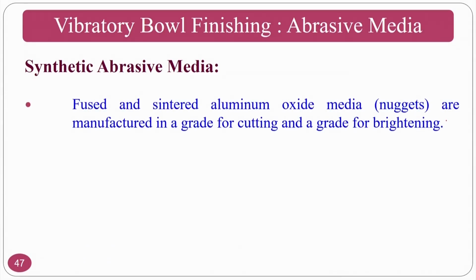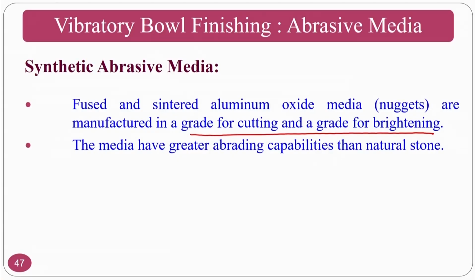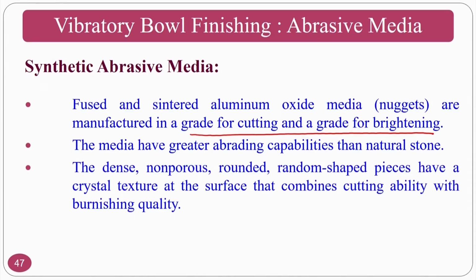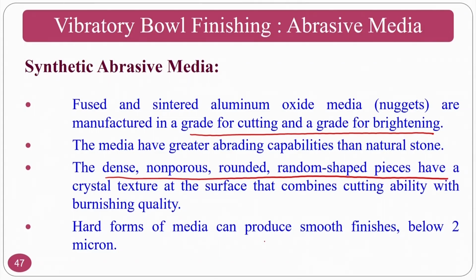In synthetic abrasive media, what we have to see is fused and sintered aluminum oxide medium. These nuggets are manufactured at the grade for cutting and the grade for brightening applications. If people want to get surface finish and good appearance also, for that purpose you can go for sintered alumina and other abrasive particles. The media have greater abrading capability than natural stone. That means silica and granite, whatever the particles are, their hardness is very low compared to aluminum oxide. So the capability of aluminum oxide is much better compared to granite, walnut flakes and other things. The dense, non-porous, rounded, random shaped pieces have a crystal texture at the surface that combines cutting ability with burnishing quality, and hard forms of media can produce smooth finishes below 2 microns. That means you can use this process for pre-finishing applications, and for advanced finishing applications also.